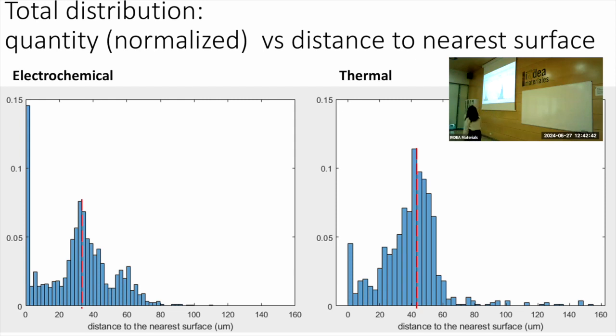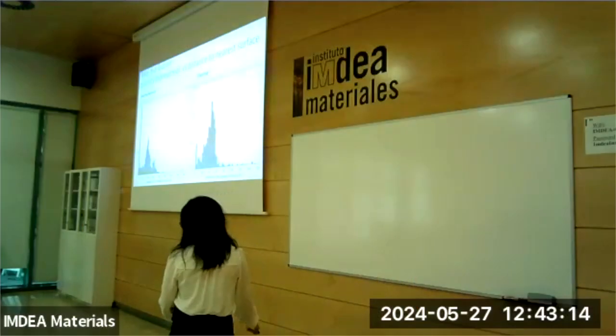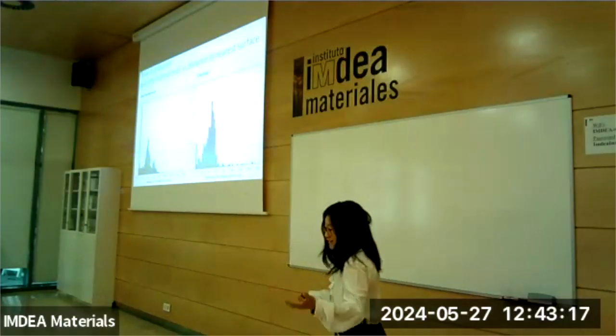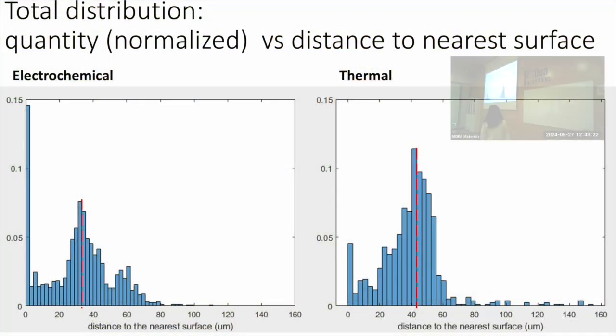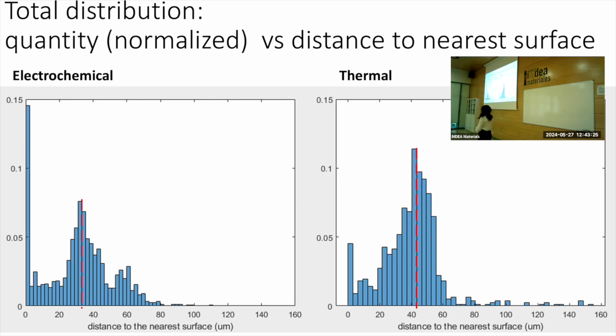As you can see, in the electrochemically charged one, the majority are distributed 20 to 40 microns from the nearest surface. But in the thermally charged one, this shifts towards 40 to 50 microns from the surface. You can also see there's a good amount of surface cracks, but compared to the thermal ones, most of those are distributed inside and even deeper inside. So what could be the reason? This is actually still a work in progress. We got this result about 2 weeks ago. So we think maybe this has something to do with our hydrogen distribution.